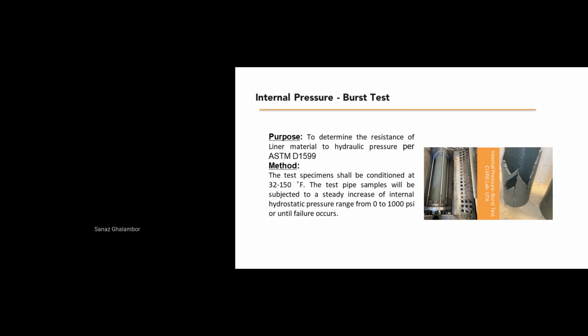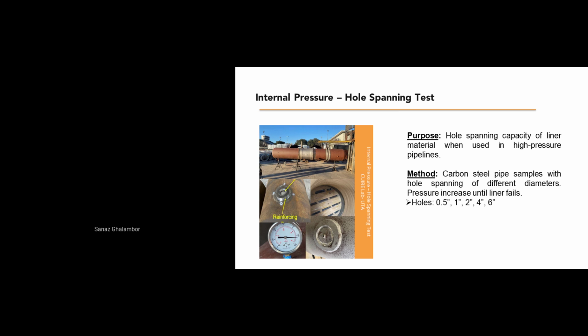We also have done internal pressure burst test based on ASTM D1599 to determine the resistance of the liner material to hydraulic internal pressure. And also we have done internal pressure hole spanning test with hole sizes of 1/2 an inch up to 6 inches. The maximum pressure that the lab could go to was 600 psi. So all the samples could pass the test up to 600 psi with no failure. And we kept those pipes at that high pressure for 10 days without any failure or issues.